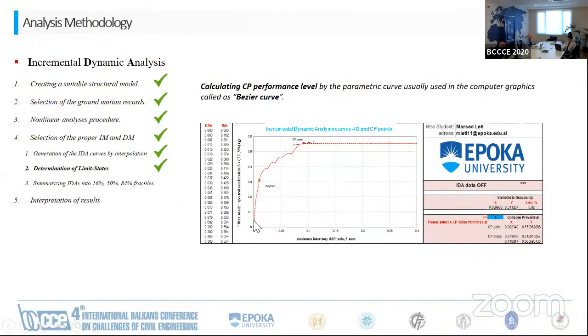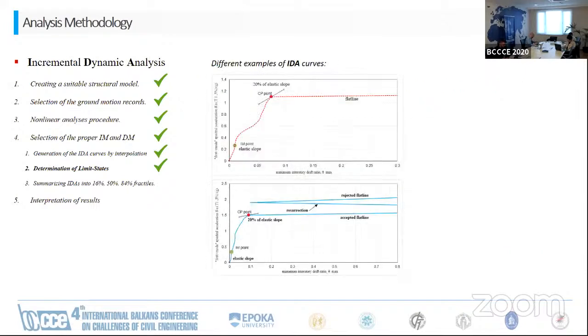And considering that the curve might be very complex for the incremental dynamic analysis, it may happen that we have different collapse prevention points. And basically from the research and previous studies, the collapse prevention point should be considered the one which happens at or before the 10% of damage measure. For this case, we are using an algorithm taken from the Bezier curve, which has been used especially in computer graphics and is very easy for interpolating the results and finding the respective values, especially by using a piece of script or computer programming.